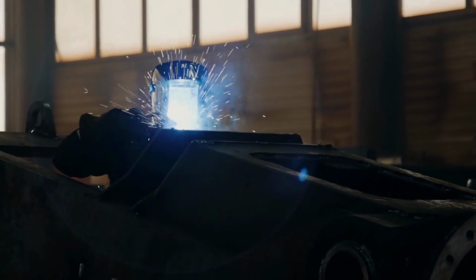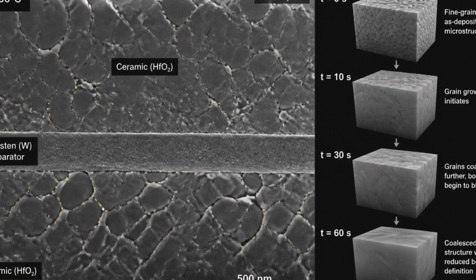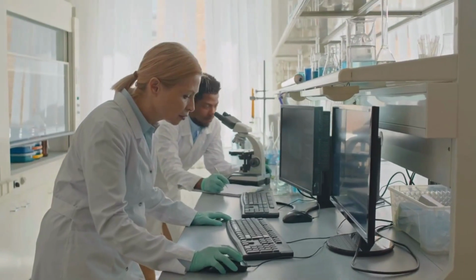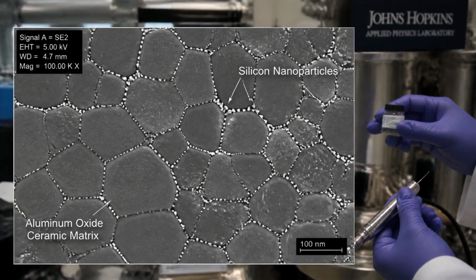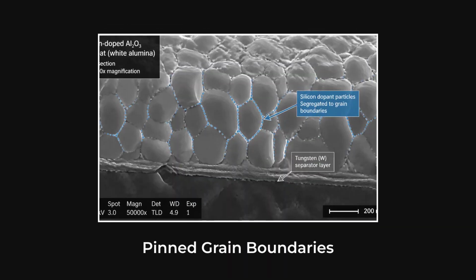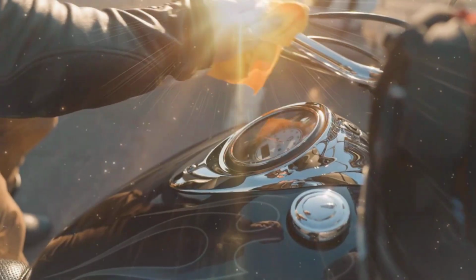This metallic barrier completely blocks the high-temperature reaction, yet the ceramic coating still faces the threat of grain growth. Under extreme heat, the ceramic's microscopic grains naturally coarsen and expand, turning the white surface dull and gray. To preserve its whiteness, engineers introduced nanoscale silicon dopants. These nanoparticles settle at the grain boundaries, pinning the microstructure in place and keeping the shield highly reflective.